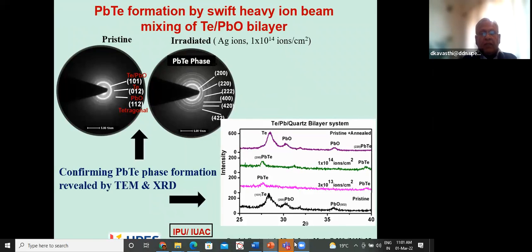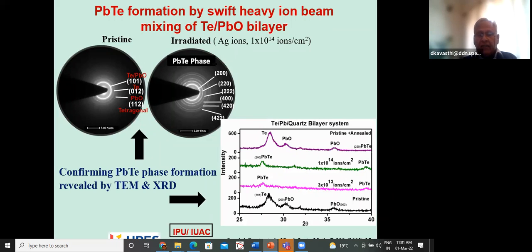One example is a tellurium film on lead oxide bilayer, irradiated by silver ions at 10¹⁴ ions/cm². X-ray diffraction shows that the pristine sample has tellurium and lead oxide peaks, but as you irradiate, lead telluride phase starts forming. The top curve shows the pristine annealed film — annealing alone leads to stronger lead oxide formation, not mixing. Ion irradiation enables mixing of tellurium and lead to form lead telluride, proven by selected area diffraction patterns showing the corresponding rings.